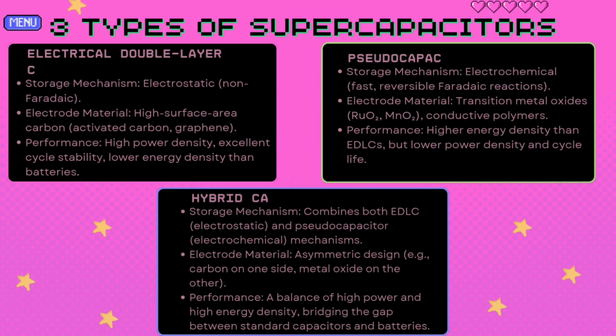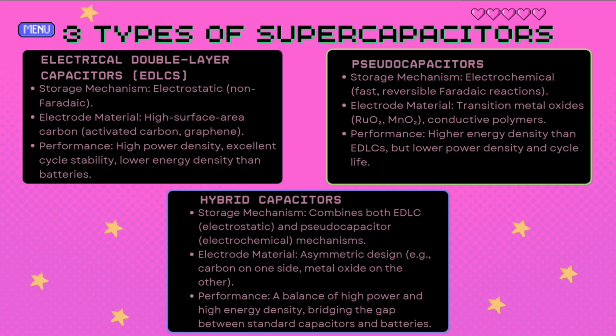Okay, so I'm going to briefly cover the three main types of supercapacitors, which are EDLCs, pseudocapacitors, and hybrid capacitors. EDLCs are the simplest. They store energy electrostatically, meaning they physically absorb ions onto the high surface area of activated carbon to form a double layer. They are known for excellent cycle life and high power density, but they have the lowest energy density. Pseudocapacitors use a fast, reversible Faradaic redox reaction on the surface of the electrode materials, usually transition metal oxides like ruthenium and manganese oxide. This chemical change allows them to offer much higher specific capacitance and energy density than EDLCs, but they generally have a lower power density and a shorter cycle life.